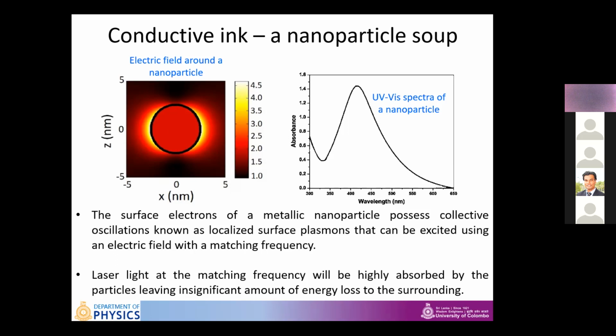If we look at how this particle absorbs light at different frequencies, so different wavelengths, we can see a distinct peak at a specific wavelength, as shown in the right-hand side picture. The right-hand side graph has wavelength on the x-axis and absorbance on the y-axis. As you can see, for this particular nanoparticle, which is silver, around 420 nanometer wavelength there's a peak in absorption. That is the resonance peak. At this specific frequency or wavelength, the nanoparticle fully absorbs the light energy, passing a negligible amount of energy onto the substrate, therefore minimizing the heat damage to the substrate.